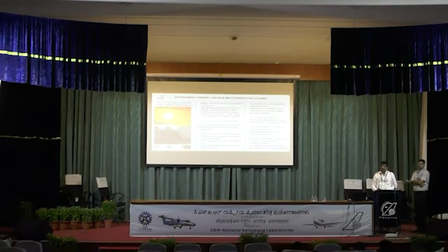Yeah, you have done thermal cycling as well, right? Yes, we are doing thermal cycling as well. For thermal cycling there are some ASTM standards, wherein we have to go up to a certain temperature, typical of gas turbine engine conditions, 1100 degrees centigrade, and then cool suddenly. Like that we have gone up to more than 100 cycles.